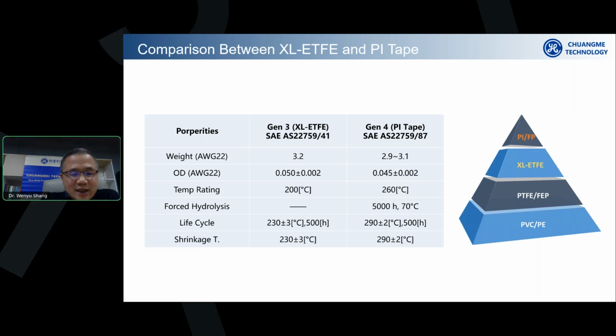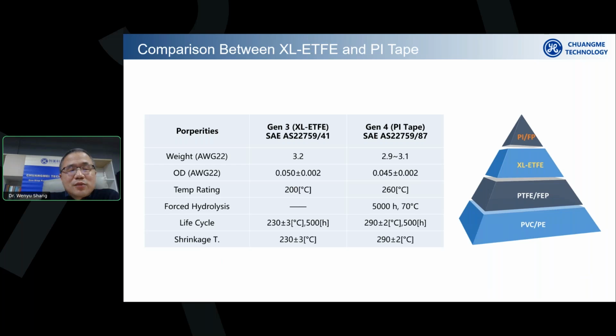So as you can see, the most important performance comparison is about the temperature rating. So the third generation calls for 200 degrees C, and fourth generation calls for at least 260. There are some cables called for 280 degrees C, but it's a very small application area in the industry. So it's 200 versus 260, and we can make both materials available at Tromei and offer to our customers, and help our customers to employ the material in their cable applications.